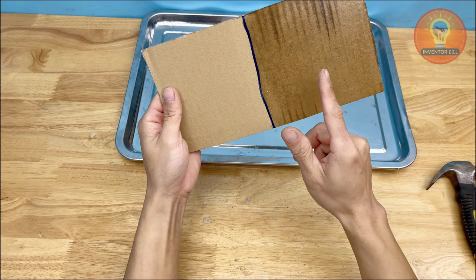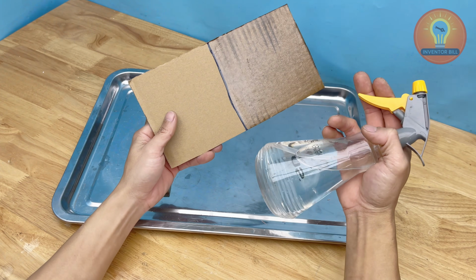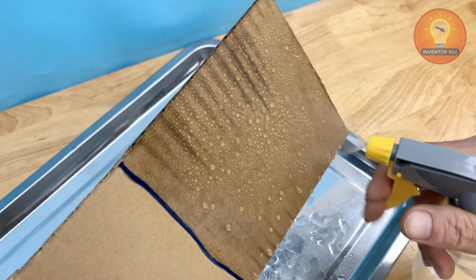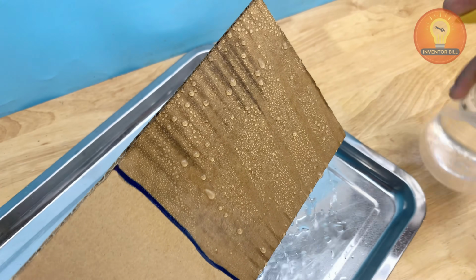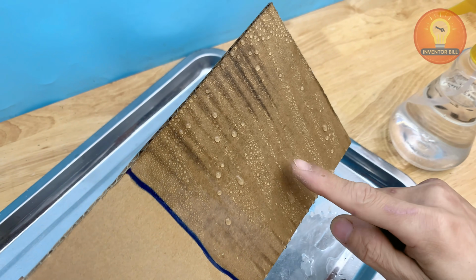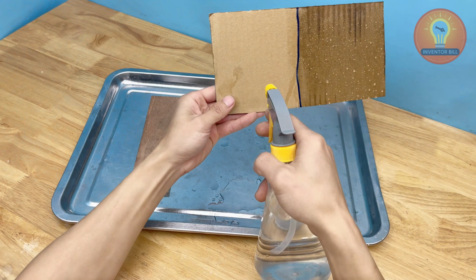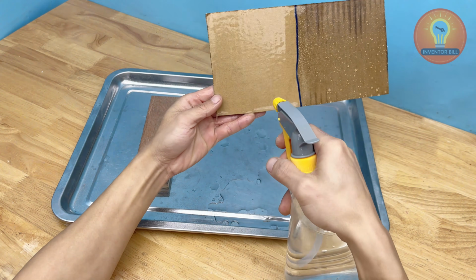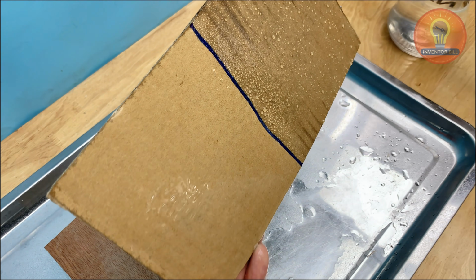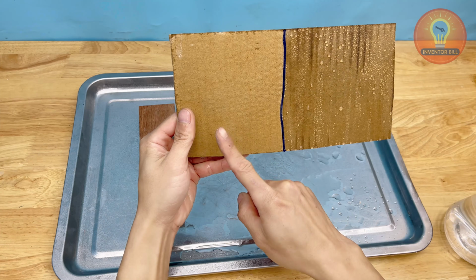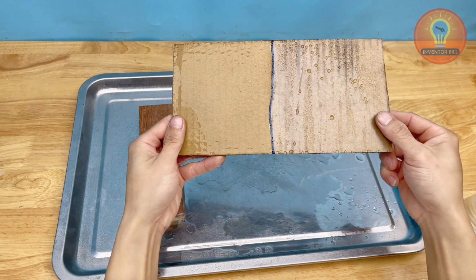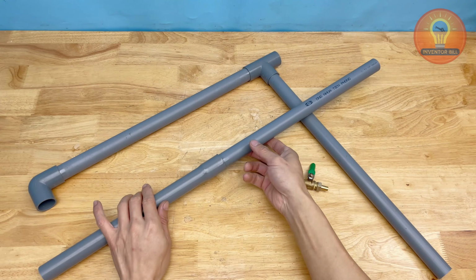Check the cardboard. Pour water over both sides. Watch closely. The untreated side absorbs water immediately. It softens, weakens, and begins to break down. The treated side remains unchanged. Water stays on the surface. No absorption, no damage. This is where the difference becomes obvious. Not just protection, but resistance.